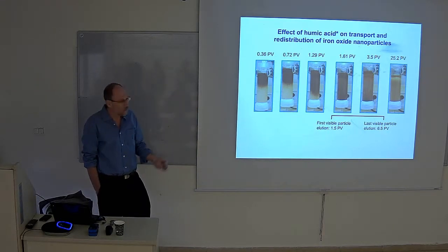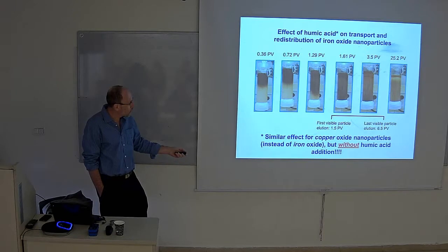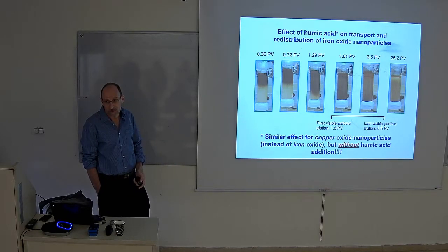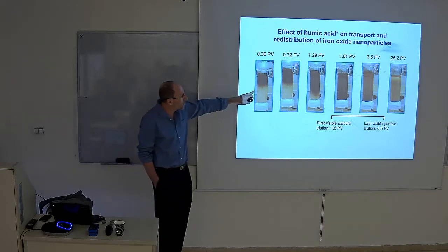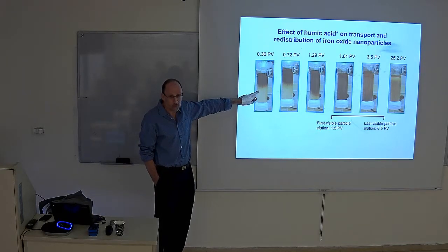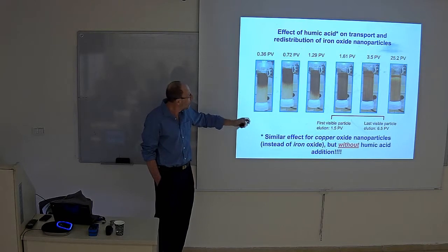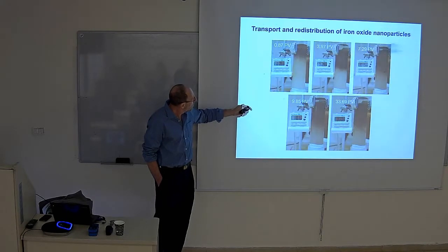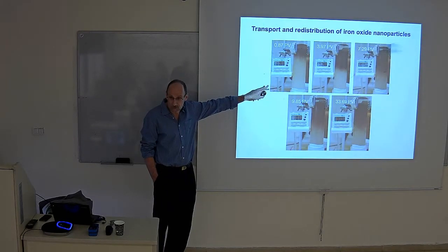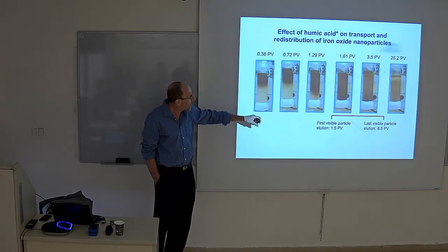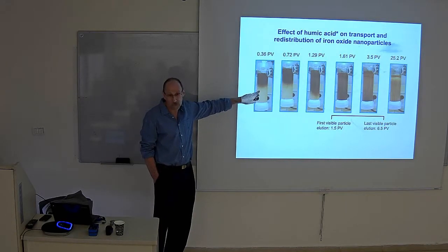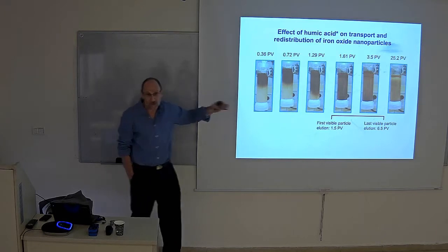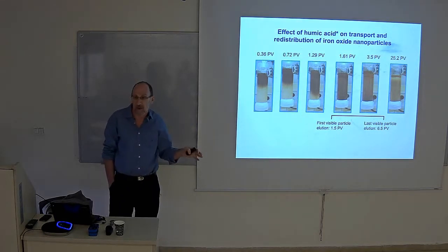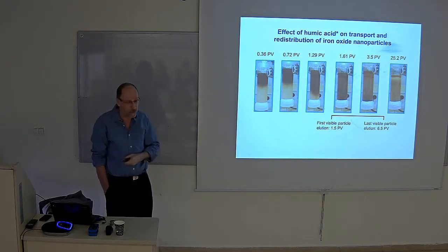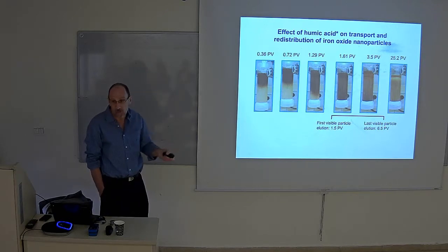So, okay, let's see what happens with copper. Took copper oxide particles without humic acid, they move just as fast. Okay, so in other words, this is what the magnetite did, or the iron oxide particles with no humic acid. This is what the iron oxide did with no humic acid. The copper with no humic acid moves like this. Okay, so you can't even generalize and say all metal oxide nanoparticles are not mobile. Iron and copper behave very, very differently.